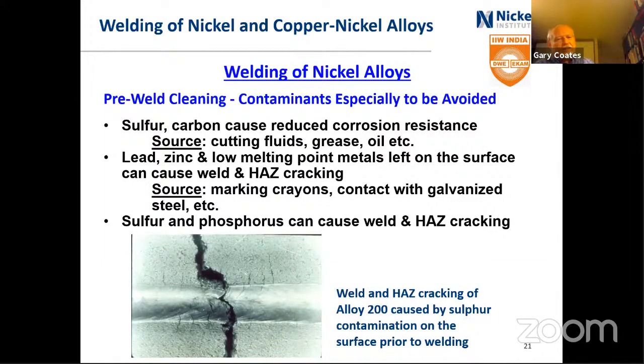And the picture is a very famous one. It's probably about 60 years old now, but it is one of an alloy 200 which had sulfur contamination on the surface prior to welding, and it caused cracking. The sulfur goes along the grain boundaries and just spreads like crazy, almost like it is a liquid metal embrittlement situation. But anyhow, it's very serious. So cleanliness is very important for all the nickel alloys.